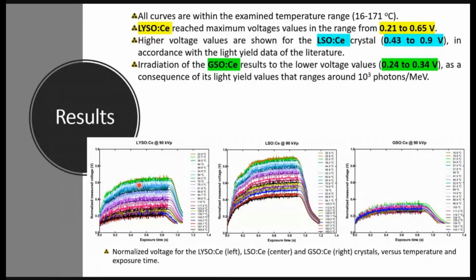The second most powerful scintillator is the Lutetium-Yttrium scintillator, and we can see that the produced voltages range from 0.21 to 0.65 volts. The third crystal is the cheap gadolinium-based crystal with produced voltages from 0.24 to 0.34.